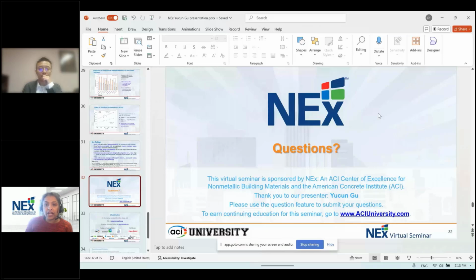So one of the questions we have is how thixotropy affects the interlayer bond of 3DCP, and also does SAP affect the structure build-up rate? Okay. We divided the thixotropy into two parameters in our case. The flock represents the initial 5 minutes, and the ADs represent a later stage, from 5 minutes to 30 minutes. I do think it is closely related to the printing process and your printing setup. In some papers, it also indicates the bond performance is closely related to the ADs.